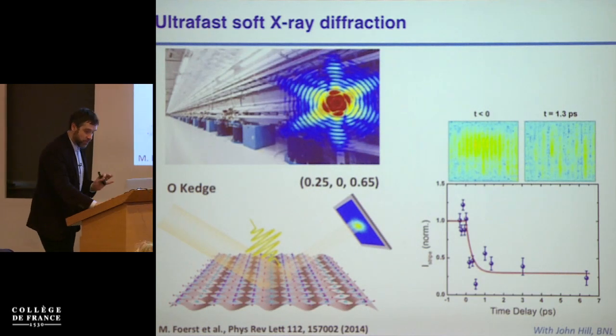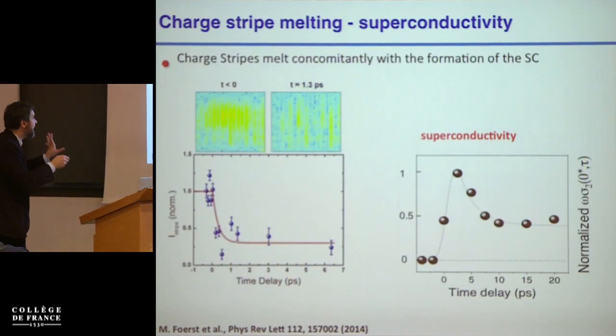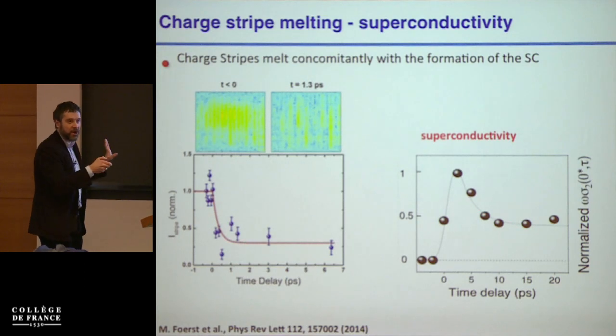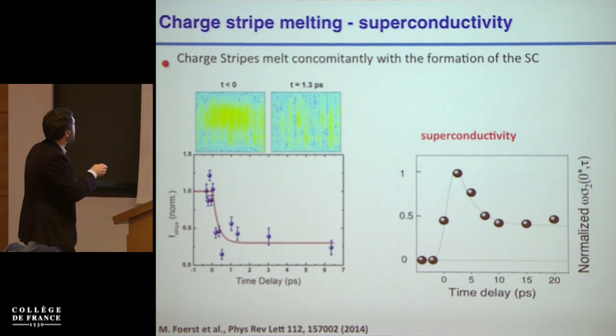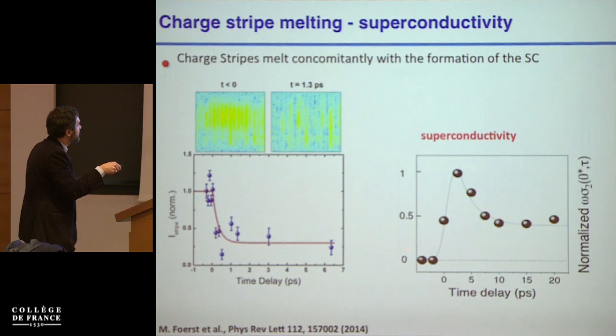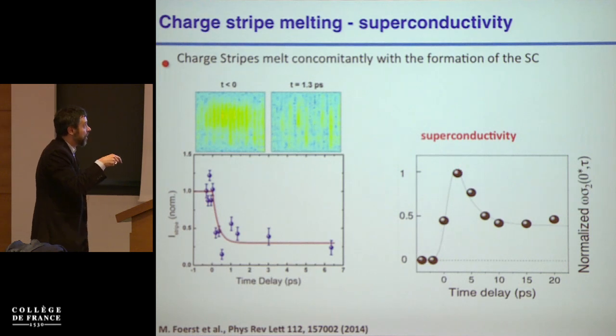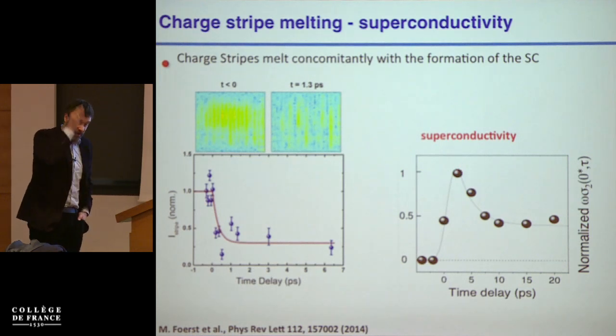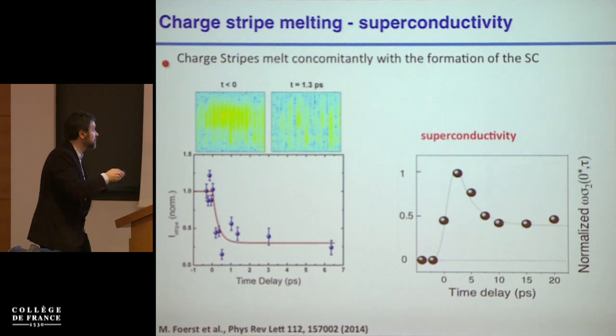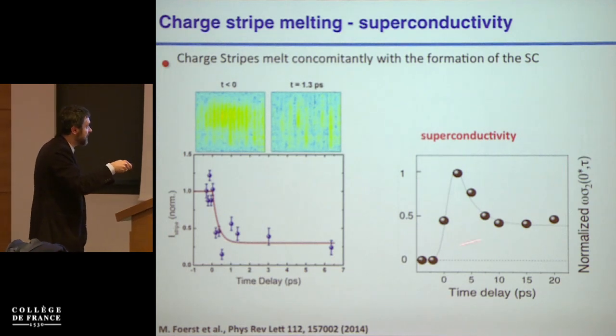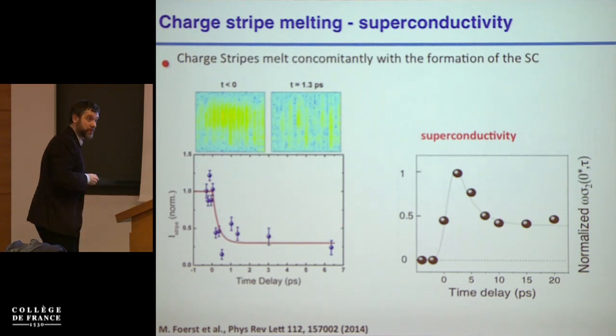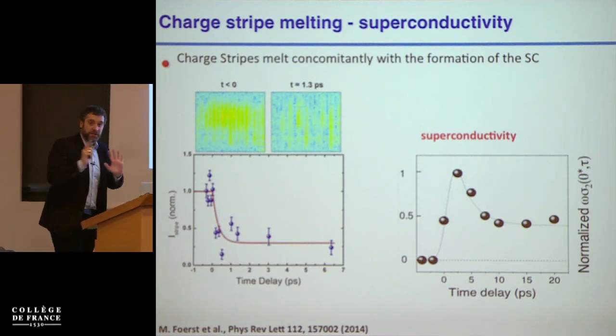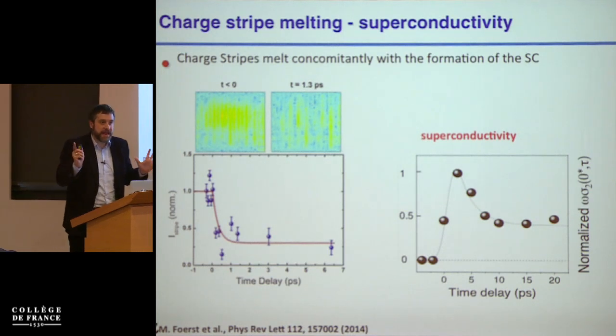What we can conclude is that, if we accept the fact that these are two slightly different compounds, to zero order, melting these stripes is on the same time scale as the formation of this coherent coupling between the planes and the superfluid density. Here I'm plotting the superfluid density as a function of time that goes up in about 1 picosecond, and here I'm melting the stripes that go down within 1 picosecond. So to zero order, this is something that we can accept.